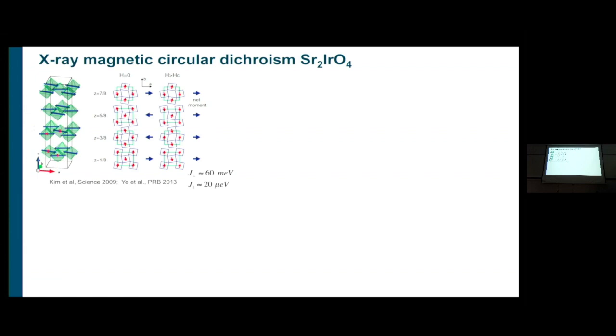And this stacking of this net moment, every layer has a net moment pointing to the right, to the left, to the left, to the right. So that's how the little moments are stacked along the z-axis, but it's an antiferromagnetic structure. So at zero field, if you apply no field, everything cancels. It's an antiferromagnet with no net moment. You cannot do XMCD. You can only do resonant magnetic scattering.